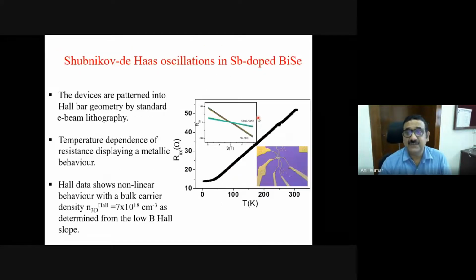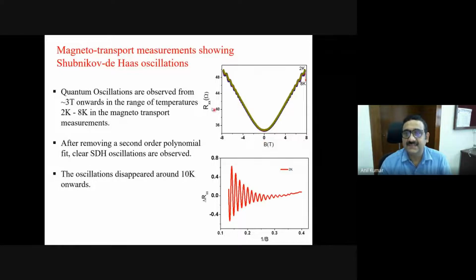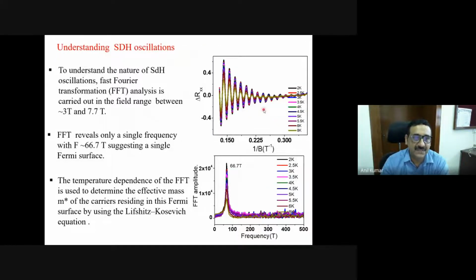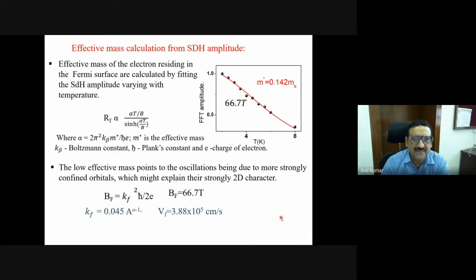But very interestingly, if you start applying a magnetic field, and look at the resistance as a function of applied magnetic field, we started getting, for this Sb-doped BiSe, very nice oscillations. From there, we can subtract the background and we can get these oscillations. And this is called the Shubnikov-de Haas oscillation. And from the Shubnikov-de Haas oscillation, we can extract different parameters of this material. You can take the Fourier transform, and that reveals a lot of important information. You can calculate the effective mass of these electrons, which is only 0.142.